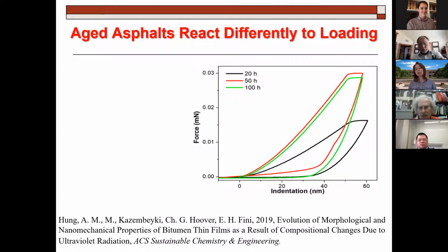And in terms of properties of asphalt, this is also very familiar. If you get a new asphalt, touch it with your hand, just with your finger. You feel the freshness and the compliance of that. That's the test that it shows. So when I touch a brand new asphalt, which is, well, not quite brand new, but 20-hour aged, the 20-hour age is the black line. If you touch it with a force of 0.01, you can indent it this much, which is sort of like when you touch a sample with your finger, you can deform it to some extent. But think of this. If I apply the same amount of force to a 50-hour or 100-hour aged one, which is red and green, I barely get half of that indentation, which is expected. It gets aged.